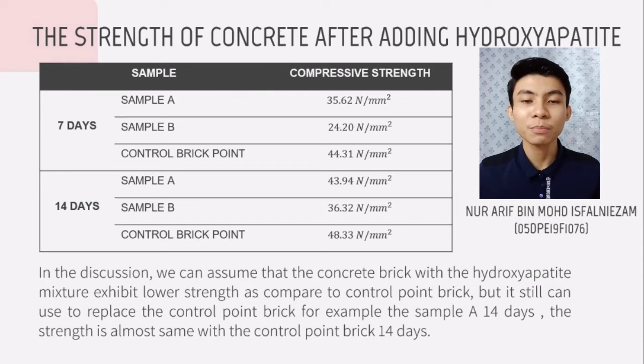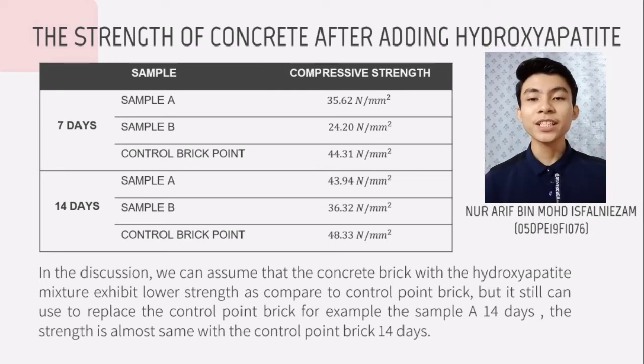Next, for the control point brick, for the 7-day, 44.31 Newton per millimeter square. For the control point brick 14-day, 48.33 Newton per millimeter square. For the discussion, we can assume that the concrete brick with the hydroxyapatite mixture exhibits lower strength as compared to control point brick, but it still can replace the control point brick. For example, the sample A 14 days, the strength is almost the same as the control point brick 14 days.